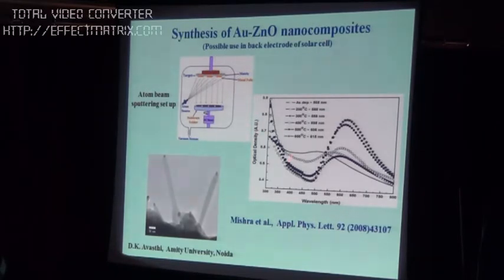And then in the absorption spectroscopy, you get one peak here, which is due to the surface plasmon resonance. Gold has a surface plasmon resonance, and this peak is because of that. By changing the temperature, this can be tuned, this can be increased and so on. And at certain conditions, you get zinc oxide rods with gold sitting on top of them.